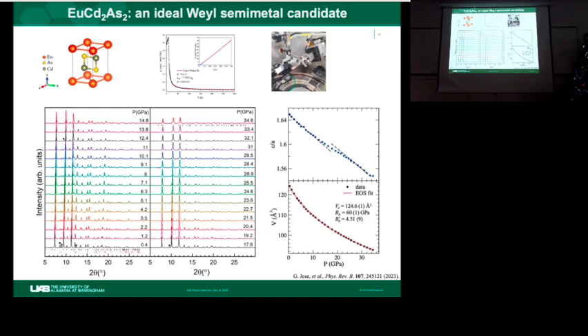Okay, take this compound as an example. So we first confirmed this compound starts with a type A antiferromagnetic state with an ordering temperature under 10 Kelvin, and we applied pressure to look at how the crystal structure is changing, because the earlier prediction is on the basis of the crystal structure needing to be conserved.